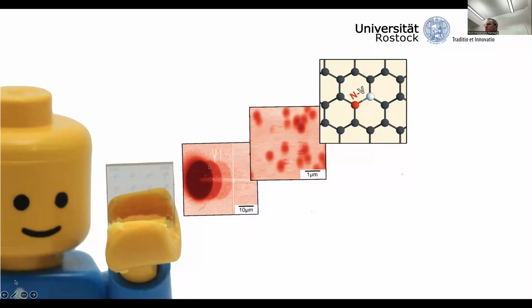We can see this as red fluorescence, and zooming into the fringe region of one of these spots, we can eventually make out little clouds of light, each of them of diffraction limited size and of the same brightness. In fact, each of these clouds is the light coming from a single nitrogen vacancy defect in diamond. So it is possible to see a single atom, essentially, a single nitrogen vacancy defect, with a good microscope.